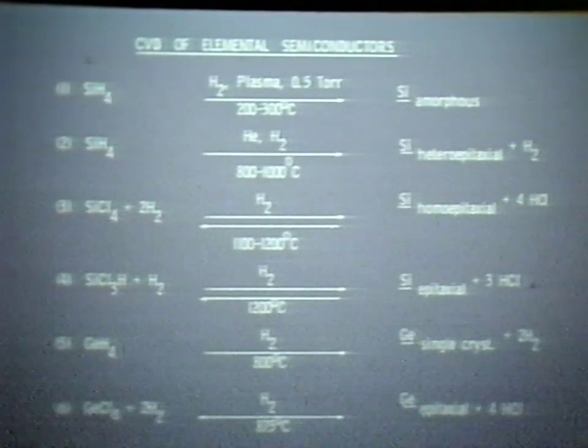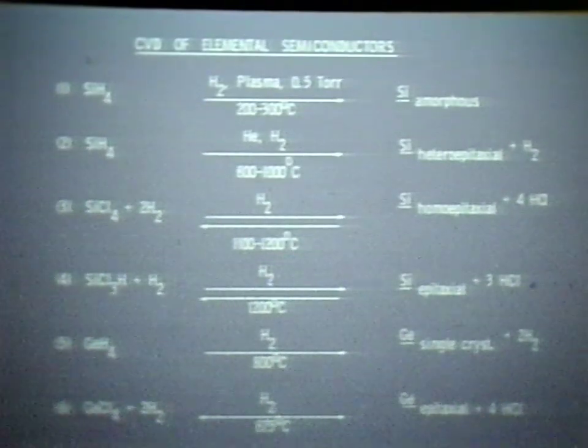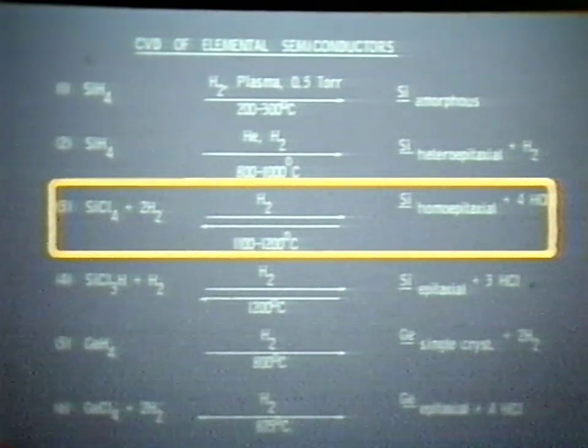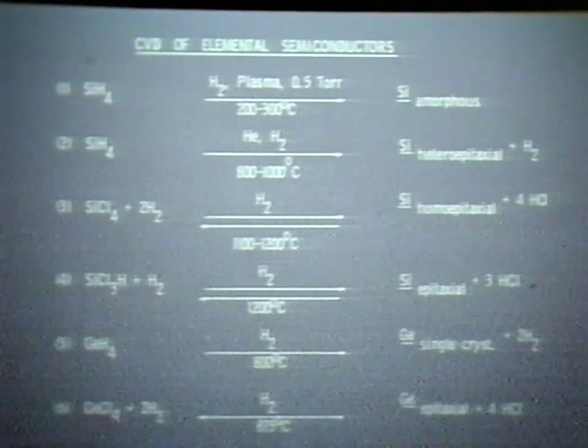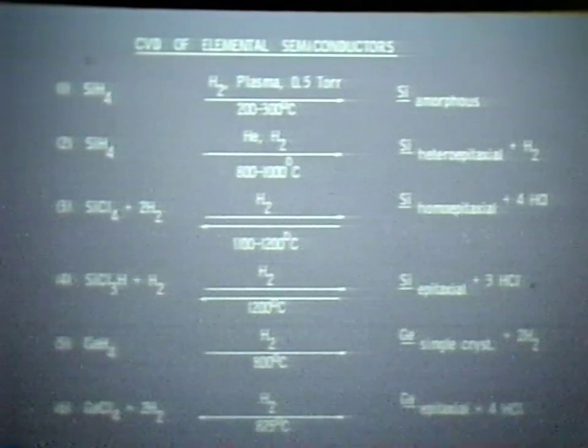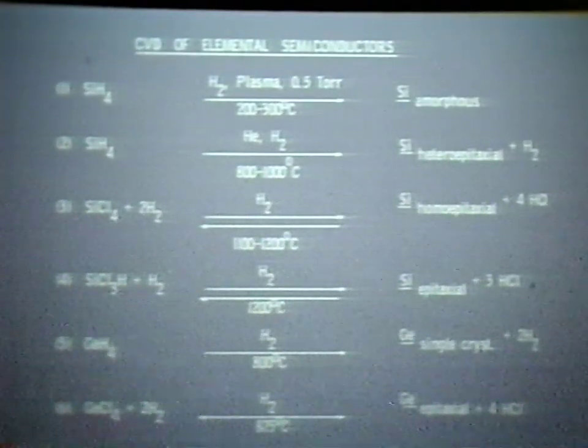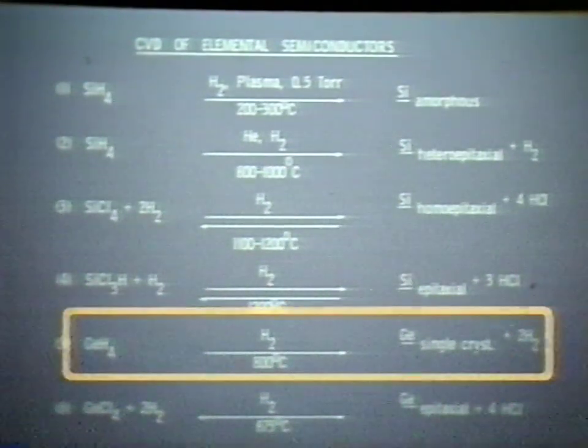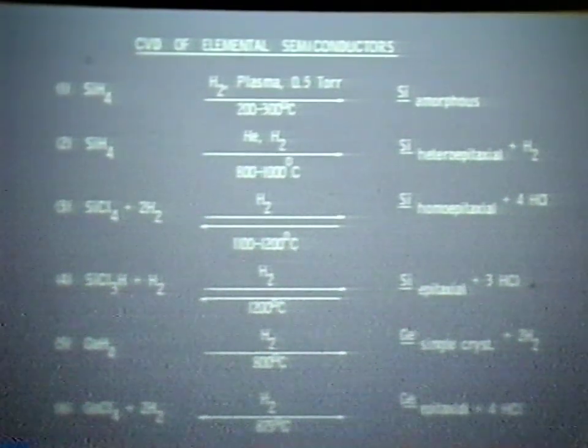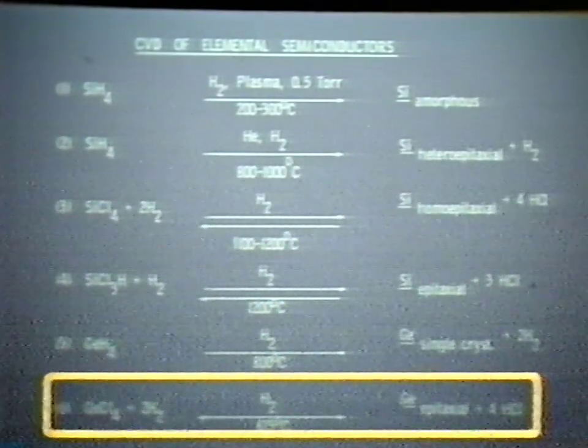That is silicon that would be produced, for example, on sapphire, where we cannot use reactions containing chlorine that would attack the substrate. Here, in this case, where we have a silicon substrate and want to produce a homoepitaxial film of silicon, we can use the chlorosilane, such as the tetrachlorosilane, or the trichlorosilane or the dichlorosilane. Any one of those silanes can be used to produce epitaxial films of silicon. The germanium species are analogous in principle to the silicon ones. Germane reacts just like the silane would, generally at an even lower temperature, and the germanium tetrachloride again can be used for the production of germanium epitaxial layers very readily. So this gives you a kind of a very brief overview.